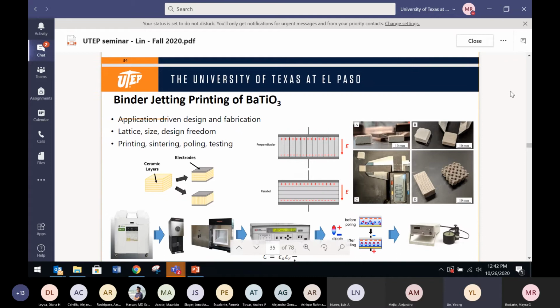And the other thing we're doing is binder jetting printing of barium titanate, which is a piezoelectric ceramic. So what we're showing here is we can control the geometry of the printed ceramics. As you see in the right image, not only can we control the lattice density, but we can also have porosity control as well. And then later on, once you do the sintering process, we do the poling process to measure its piezoelectric property. Next slide.